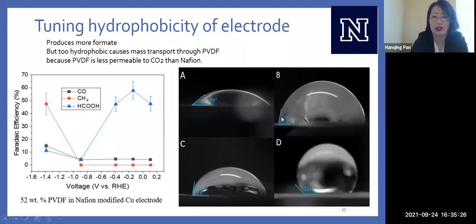And this is demonstrated here by contact angle measurements. So if you drop a water droplet onto a surface, if the surface is hydrophilic, if the water droplet likes the surface, it will spread out like figure A. But if our surface is really hydrophobic, the water droplet beads up. And so we can demonstrate here by adding more and more amounts of PVDF into Nafion, we're making our copper or metal surface really hydrophobic.